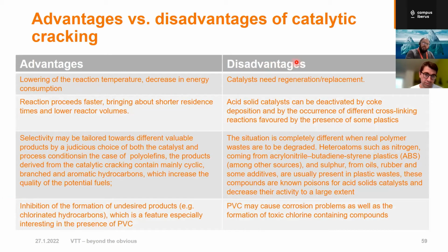On the other hand, the disadvantages of using catalyst: it needs regeneration. If you're not regenerating, then your catalyst can be deactivated very easily from the impurities. For instance, here acid catalyst can be deactivated by coke deposition. Then it stops being the catalyst. Impurities such as nitrogen coming from different plastics, for instance, ABS plastic, acrylonitrile butadiene styrene, which is very common in electronic waste, contain a lot of nitrogen. And for example, sulfur: rubber or tires can contain a lot of sulfur. These types of impurities can deactivate catalyst easily. And for instance, if there is PVC, it can also cause corrosion and form toxic chlorine containing compounds.